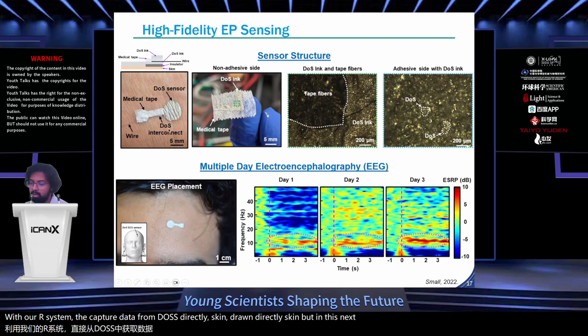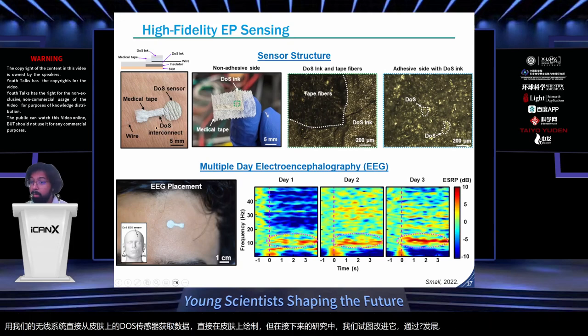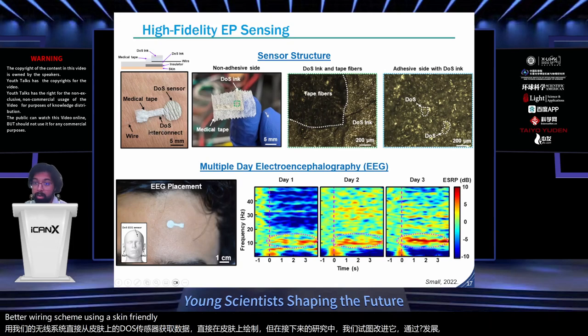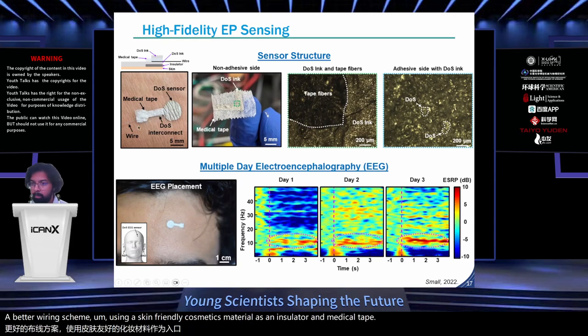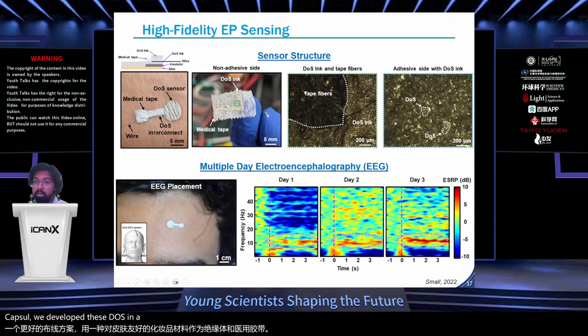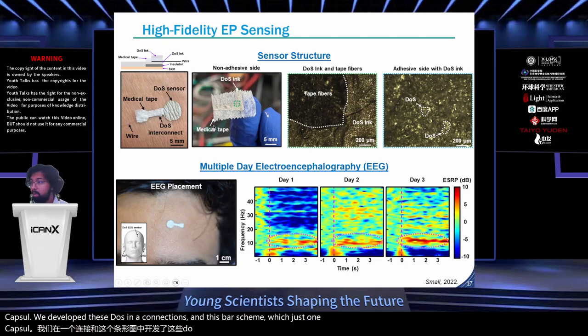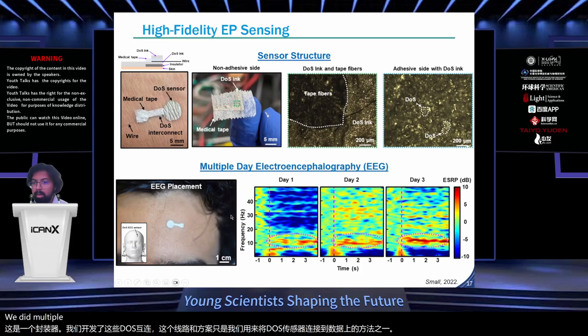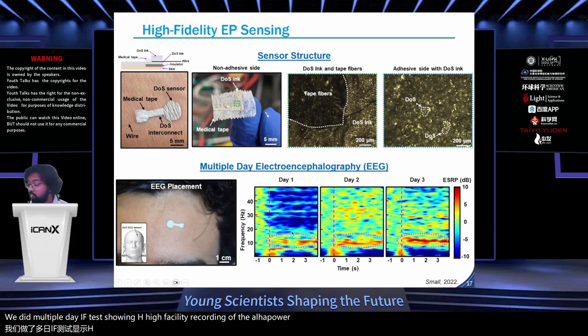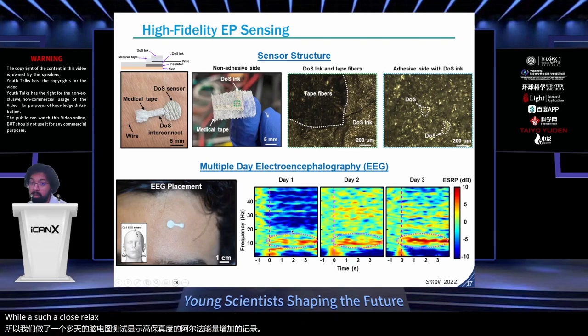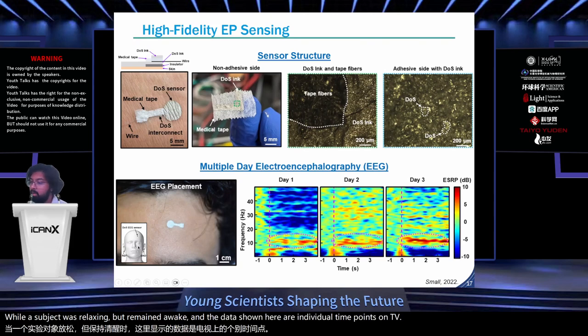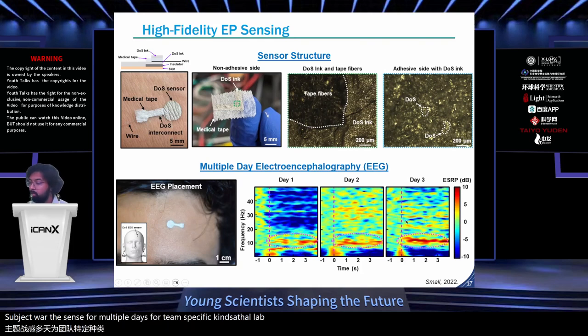But in this next study, we tried to improve that by developing a better wiring scheme using a skin-friendly cosmetics material as an insulator and medical tape as an encapsulator. We developed these DOS interconnections. This wiring scheme was just one of the methods we utilized to patch DOS sensors for our data acquisition. We did a multiple-day EEG test showing high-fidelity recording of the alpha power increasing while the subject was relaxing but remained awake. Data shown here are individual time points. The subject wore the sensor for multiple days.